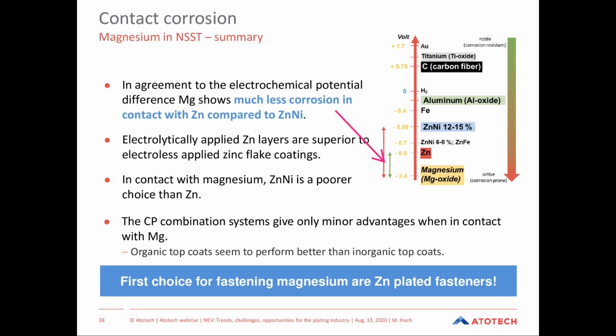Electrolytically applied zinc layers are superior to electroless applied zinc flake coatings. As already seen, zinc nickel is a much poorer choice than zinc. And CP combination systems give only minor advantages in this case when in contact with magnesium. And organic top coats seem to perform better than inorganic top coats. And again, the first choice for fastening magnesium are zinc-plated fasteners.